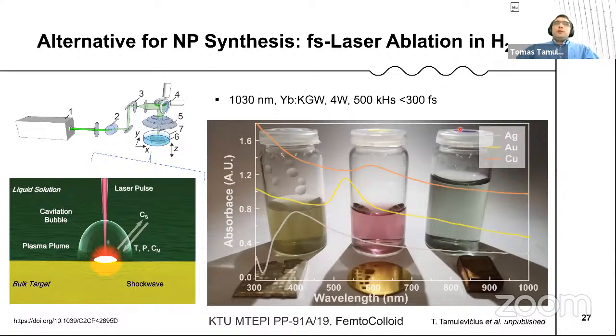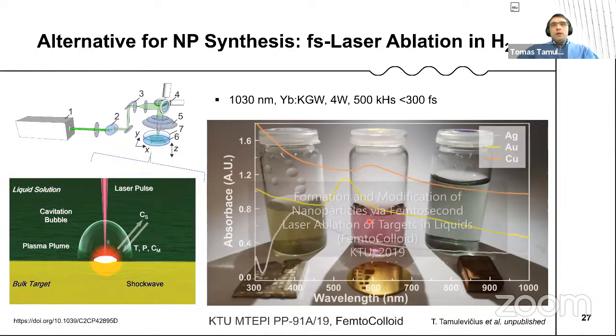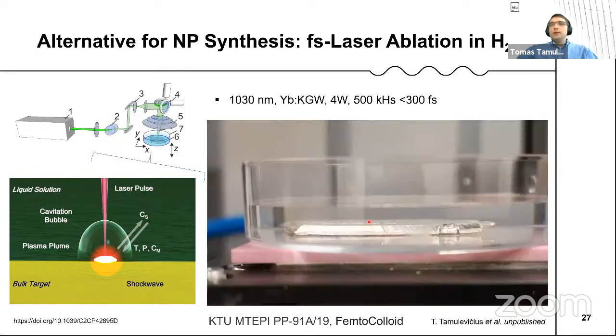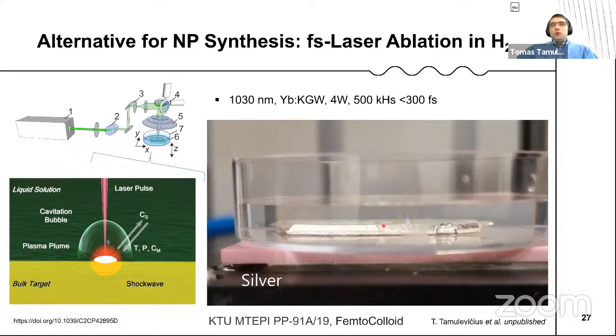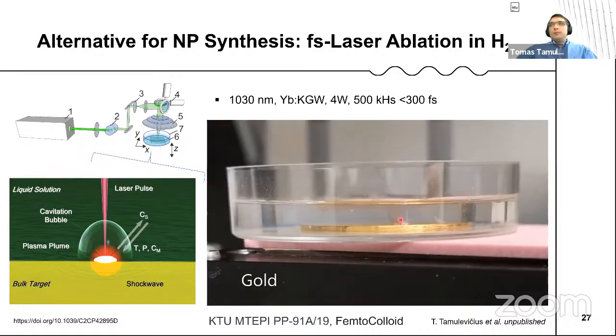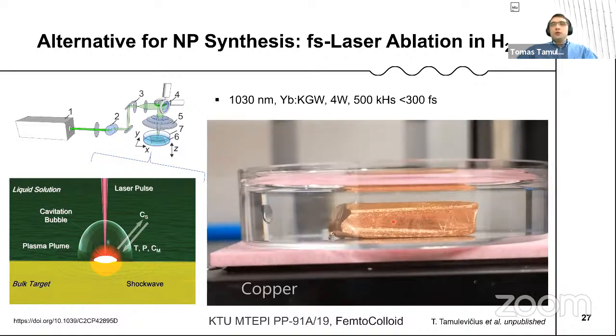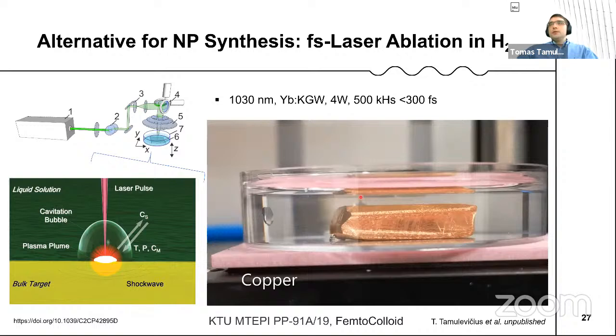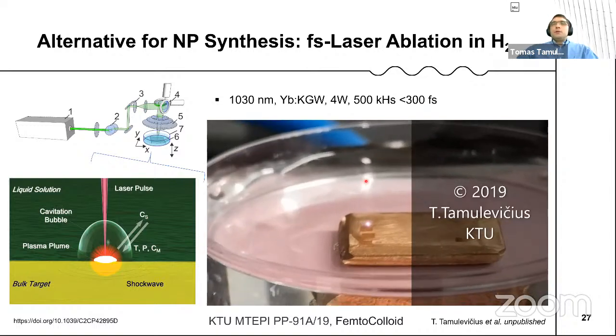And there is also an alternative to the chemistry. You can use a femtosecond laser to ablate the target, and we use this Yb:KGW laser from Light Conversion to make silver, gold, and copper colloids. So you simply scan the beam at the good energy and translation rates, and you can see how this colloid is appearing. So there are many ways to make the nanoparticles, and different ways are good for different applications.